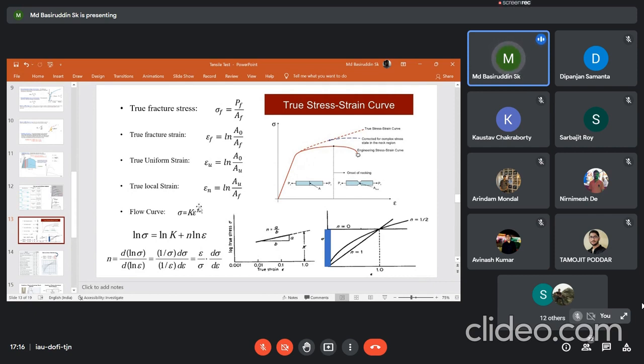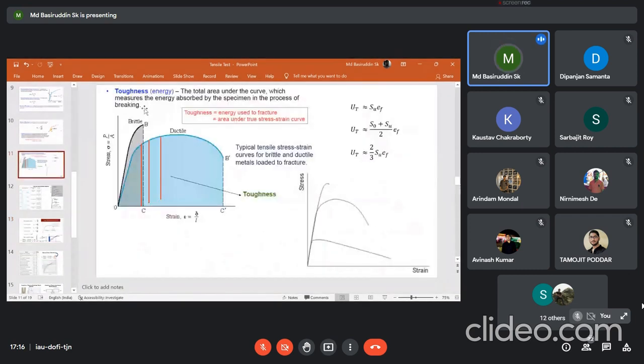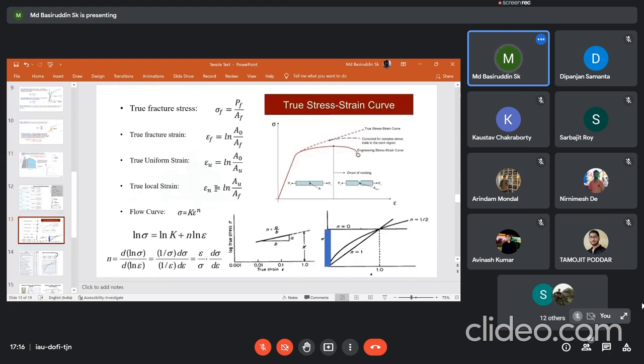Now, what does the strain hardening exponent actually tell us? It basically depends on the resistivity, that means during deformation the material will try to resist the deformation. That can be measured by measuring the strain hardening exponent. Mathematically, if we take the log on both sides and plot ln sigma versus ln epsilon, whatever slope we find is the strain hardening exponent, and the intercept is the strength coefficient of that material.